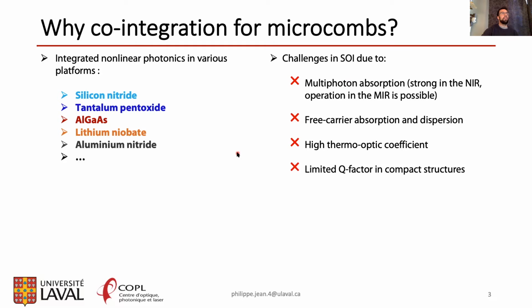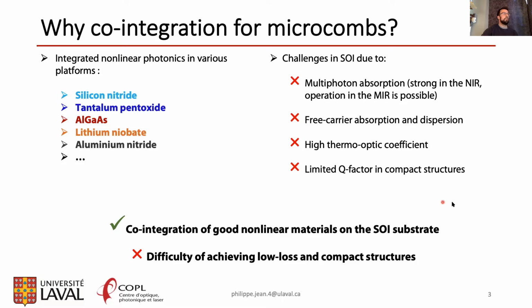although silicon has a very high nonlinear index, it has been less leveraged, I want to say, for nonlinear photonics because of silicon multiphoton absorption, as well as free-carrier absorption and dispersion, its relatively high thermo-optic coefficient, and also in many cases, the limited quality factor that can be achieved in compact structures. Although I want to mention that very high quality factor can be achieved in multi-mode and relatively bigger structures. So our solution to this is to co-integrate other materials that are not silicon that have good nonlinear properties directly on the silicon on insulator substrate.